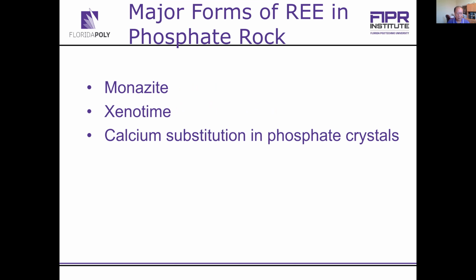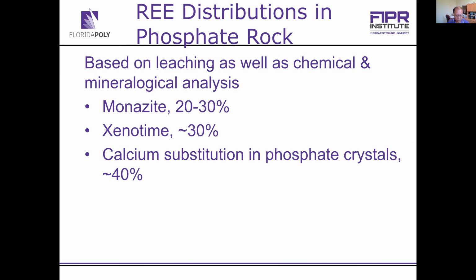In that regard, generally in the phosphate rock, we have monazite, xenotime, and calcium substitution in the phosphate crystals. So there are three forms of rare earth occurrence in phosphate ore in general. And also based on some leaching tests and chemical analysis, we quantified the rare earth elements occurrence in phosphate rock: roughly 20 to 30% as monazite, about 30% as xenotime, and the remaining as calcium substitution in phosphate crystals.